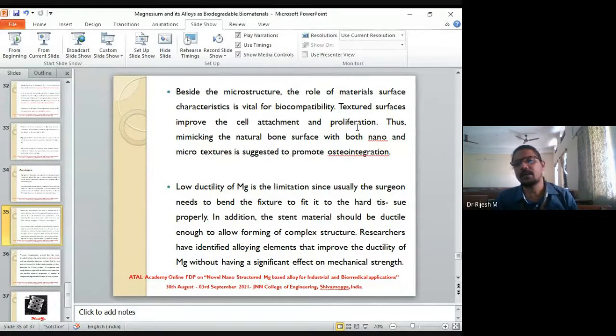Magnesium is not a soft material because of the HCP structure. They do not have slip planes to deform. Their slip planes are very hard. So they have very limited slip planes, basal slip planes. So they're not ductile. This low ductility is a problem in magnesium, because usually surgeons will use this implant by bending and fixing inside, and your material cannot do that.